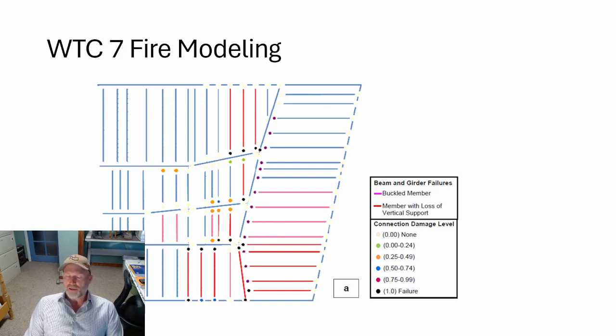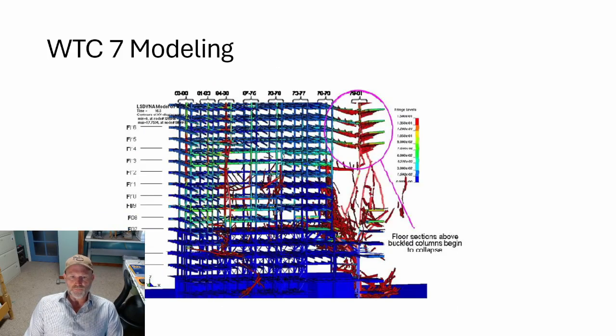But what was interesting in WTC7 is it wasn't a concentrated fire. It wasn't the loss of just column 79 in this case. It was multiple columns that lost their strength because of prolonged exposure to high elevations of temperature. And that resulted in multiple columns failing, as this image shows. So what you had is at column 79, it may have initially buckled or failed, probably through buckling. And there's some other features that hopefully I'll get the chance to address here. But once that happened, there were other portions of the structure that were also weakened by that thermal heat transfer and thermal expansion and resulting loss in yield strength.